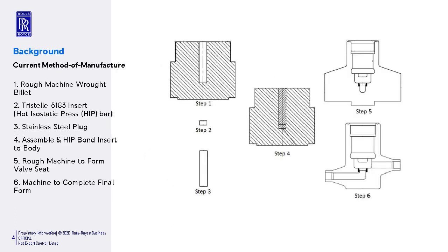So a little bit of background around the current method of manufacture. So step one, we take a large rough machined initial billet of 316L material. Step two is then to produce the Tristel insert. This is made from metallic powder that is hot isostatically pressed, hipped, into bar form and then machined into the insert. Step 3 and 4 is around producing a stainless steel plug, which is then used in step 4 to encapsulate the Tristel insert into the wrought body.